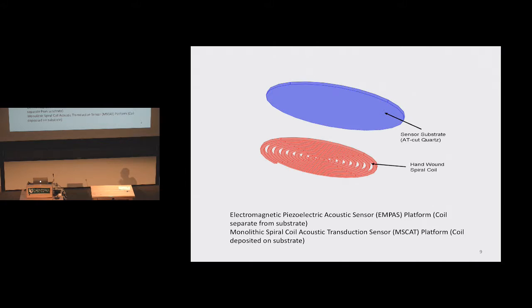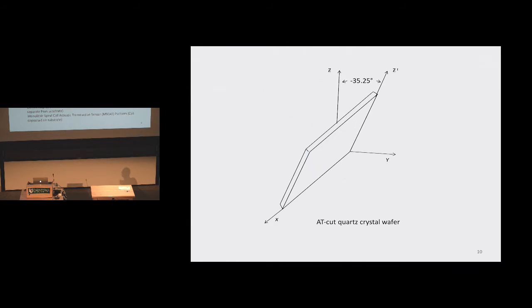Finally, the so-called EMPAS platform. The coil is separate from the substrate. It almost acts as an antenna. And this material is the piezoelectric substrate, which is often AT-cut quartz. And then finally, the so-called MSCAT, one that we've done a lot of work on at the University of Maine and published several papers, where we have the actual coil deposited onto the piezoelectric substrate to excite the bulk acoustic wave.